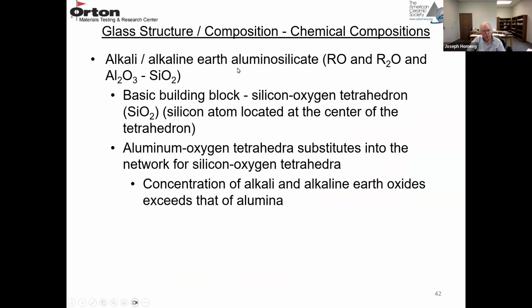And then a little more complex glass, you have alkaline earth, and then you have an alumina addition. So this is an alkaline earth aluminosilicate glass. So you have RO, R2O, and Al2O3 in this silicate-based glass. Again, the building block is still the silicon oxygen tetrahedron with the silicon atom located at the center of the tetrahedron. That's the SiO2. Actually, this is SiO4 unit.